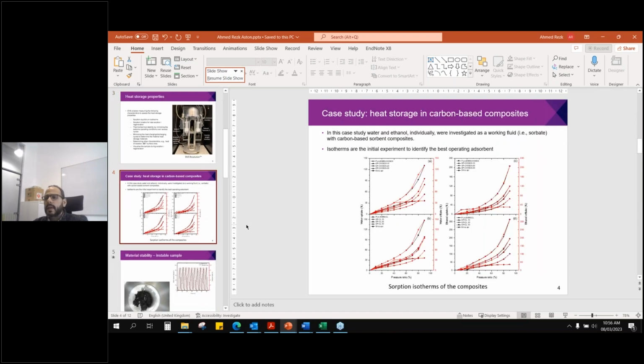So this is the first step, actually: looking at the adsorption isotherms, which tells you what material works best in terms of the equilibrium uptake. But as most of you know, it's equilibrium uptake, so the material takes time to reach this condition, and the kinetics is also important. But again, we need to look at the adsorption isotherm itself, and we're going to look later at how the kinetics comes into the context. So we characterize the material, and we have a benchmark material, which is silica gel.